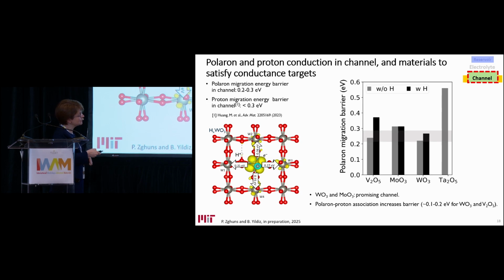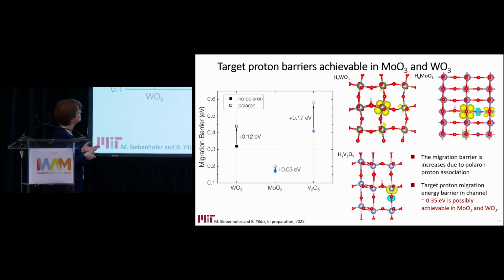And among these different oxides that we have surveyed, tungsten oxide and molybdenum oxide put us into that range, at least theoretically. Tantalum oxide is too high barrier and not conducting enough. And in addition to polaron mobility, one also has to pay attention to proton mobility so that the response is as fast as possible. And the target is 0.3 eV or lower for proton migration barriers. And we omit tantalum oxide because it's not a good polaron conductor. But then if you look at the migration barriers for protons in the presence of polarons, which could be trapping sites, the migration barriers for tungsten and molybdenum oxide are close to this targeted 0.3 eV migration barrier. Therefore, we think both of these are potentially promising binary oxides for the channel in these devices.